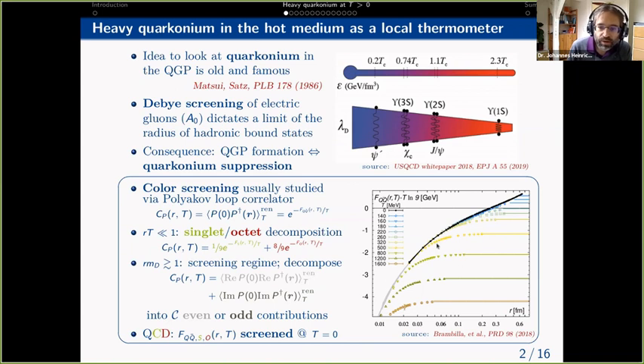At larger distances, where you're really in the range where this screening is happening, instead of singlet and octet, which can't be defined there anymore, you have to think of different contributions from different parities or charge conjugation eigenstates of the states. This can be followed essentially down to the crossover and looks very consistent. You then realize that the contribution to these free energies, and to the screening of these free energies at the crossover, is really due to the string breaking that you have in QCD at zero temperature even.